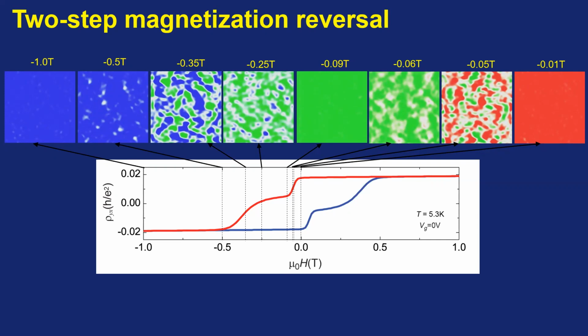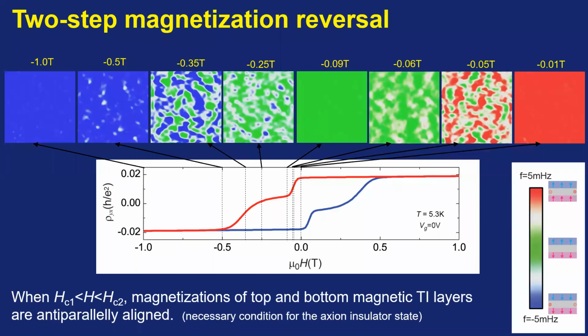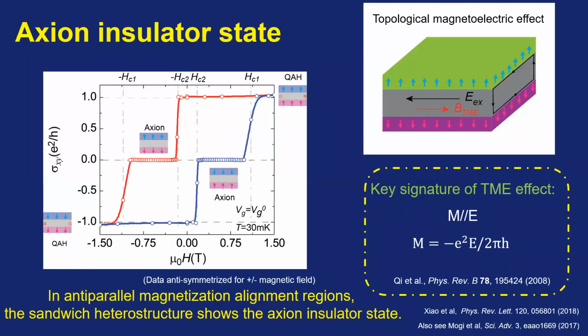So we can see at minus 0.09 Tesla, it indeed shows a uniform state here. This just means that the top vanadium layer and the bottom chromium layer have the anti-parallel magnetization alignment. So when the magnetic field is between these two HC, there is this kind of anti-parallel alignment. This is just the necessary condition for the realization of the axion insulator state. So let's see the transport result.